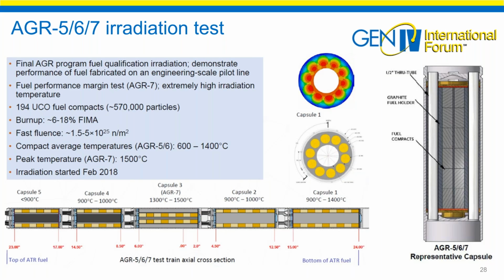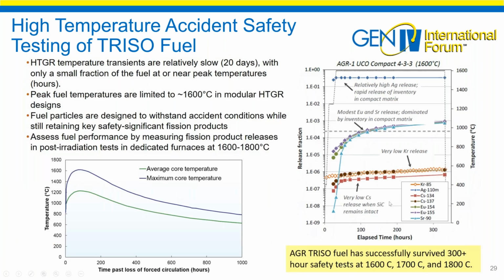Now I'm going to just show you that AGR 7, this capsule 3 here, we have fuel compacts here. We have to have a through tube for the instrumentation from the other compacts below. And the question you might ask, well, why does the temperature sort of change along here? Well, the flux in the Advanced Test Reactor would peak in the middle, of course, with a chopped cosine. And the top of the core is where the coolant comes in and it flows downward in the reactor. There's a lot of thermal analysis and neutronics analysis to determine what is happening in each one of these.